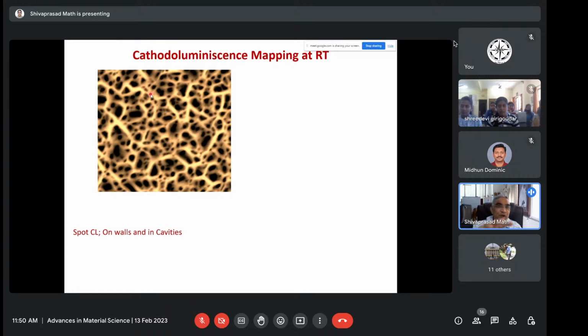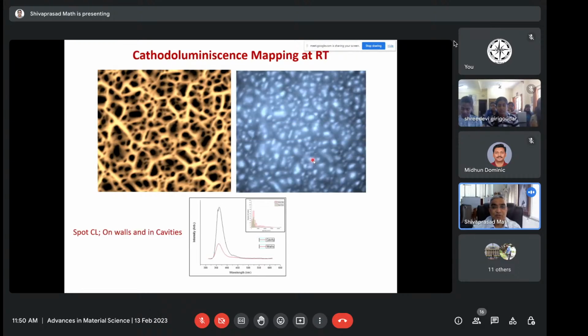They're not drilled through or anything of that sort. So we wanted to look to see how light comes out of this material. So we did what is called cathodoluminescence. Cathodoluminescence is basically photoluminescence by using an electron beam. And an electron beam, because it has a charge, can be focused into a very sharp beam, like in an electron microscope, for example. In fact, the cathodoluminescence is done in a scanning electron microscope, a field emission scanning microscope. So I can actually find out where the light is coming out of the material.